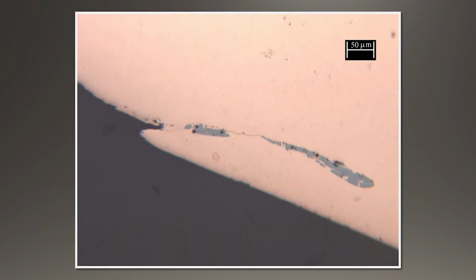Here's another cross-section of a rod, and this looks different. This was caused by the corners of the cast bar getting folded over during the hot rolling process. So once again, a lot of the defects can occur even before the wire drawing process takes place, but during the preparation of the rod.